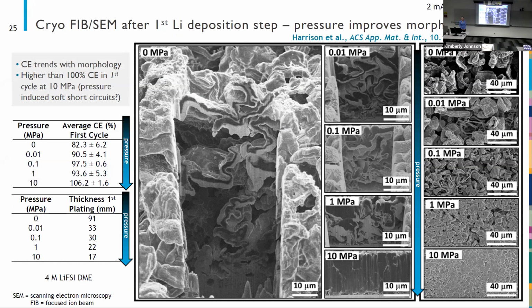So in these experiments, we're using cryogenic focused ion beam milling, gallium beam in this case, and scanning electron microscopy imaging. This is after one deposition of lithium onto copper on the working electrode. And these are the cross-sectional images that we see. We use cryogenic imaging because lithium is a very sensitive metal to beam and temperature. And so we like to freeze it and then know that we're not doing very much damage to the lithium.